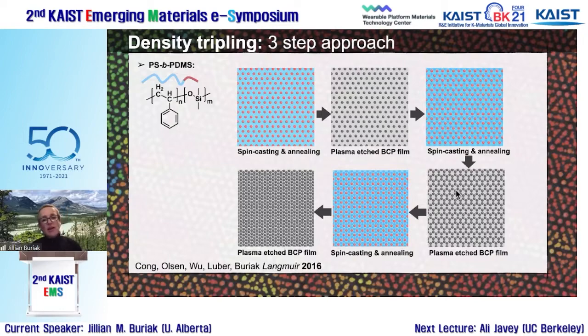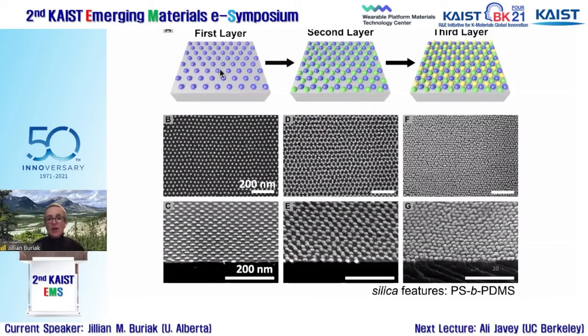If it registered, you get a honeycomb pattern. And then if you spin coat yet another layer on top of these now silica dots, would you get the triple density film? In fact, you do. Initially, up in the top in A, you can see the blue dots that represent the single layer, and then you can look at the corresponding scanning electron microscopy micrographs. And then when you put on the second layer, represented in green, you actually do get registration. At the time, we had no idea, but they do register.